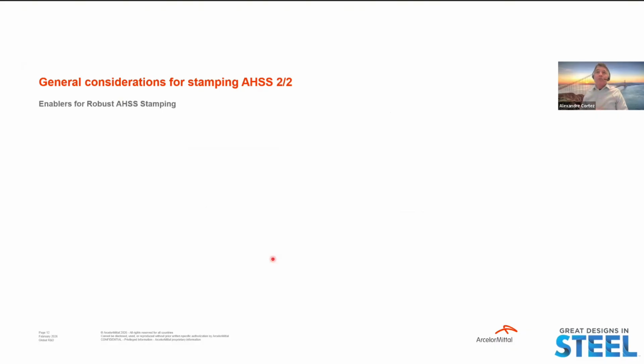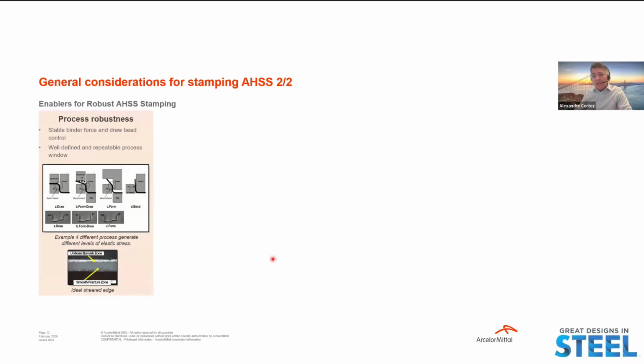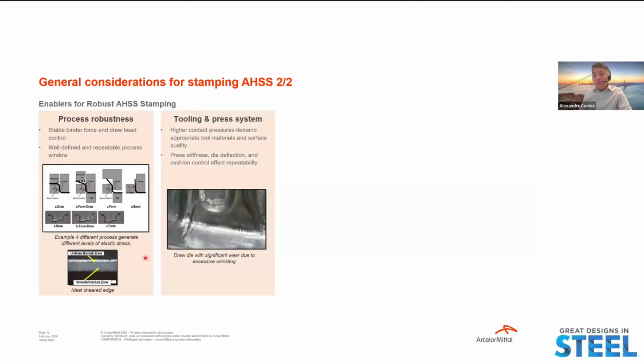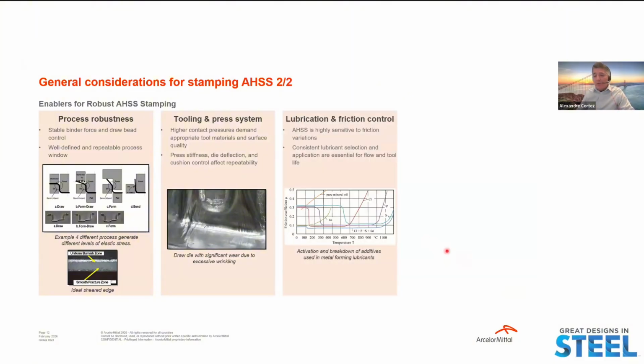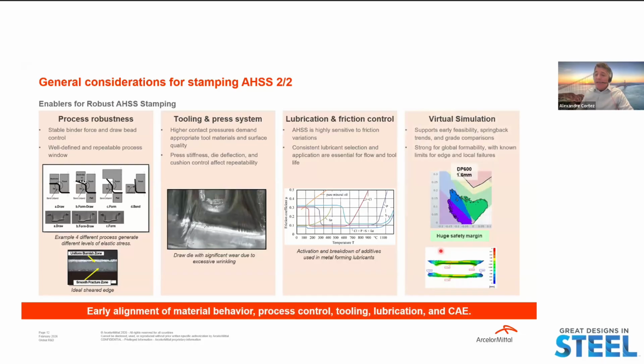Okay. I would like also to highlight enablers for robust advanced high-strength steel stamping. First, process robustness: stable binder force and draw bead control, plus a well-defined and repeatable process window. As you can see here in the graph, this is an example of 4 different processes generating different levels of elastic stress. And tooling and press: higher pressure demands correct tooling materials and surface quality. Press stiffness and cushion control affect repeatability. And lubrication and friction control. Advanced high-strength steel is friction sensitive, so consistent lubricant selection and application are essential. And CAE supports feasibility, and the springback trends and edge local failures need special attention.